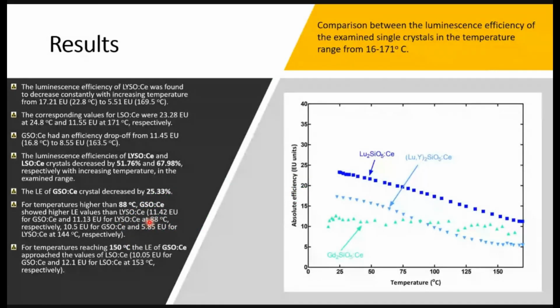In the next slide, we can see a comparative analysis of the three crystals. We can see that the lutetium and lutetium-yttrium crystals have a similar signal drop-off with increasing temperature. And we can see that in these two crystals, we have a signal reduction of more than 50% and up to almost 70%. This is a very big reduction for a detector. On the other hand, the cheaper detector, the gadolinium-based detector, appears to be robust in higher temperatures, and we can see only a 25% reduction in the signal of this detector.